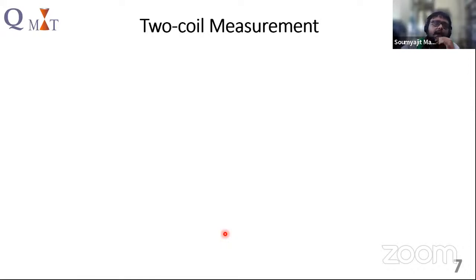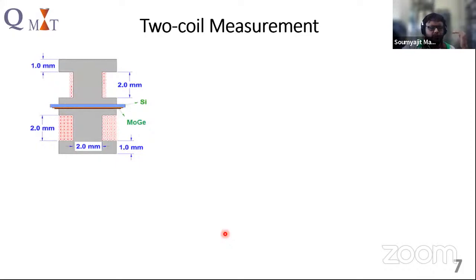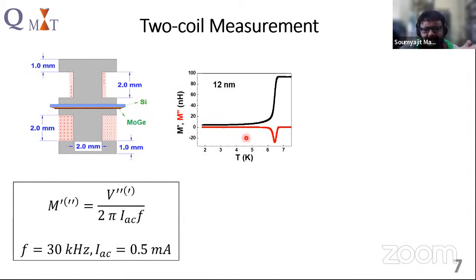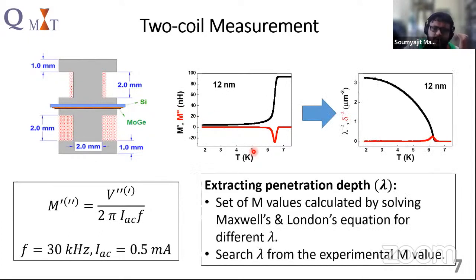And now we are going to the two-coil measurements. In this measurement, we place the sample in between two coils, and we pass a small AC current through the primary, and we pick up the voltage in the secondary. The response of the superconducting sample is captured in the mutual inductance. From that we can extract the penetration depth by solving the Maxwell equations and the London equation for the whole setup, because we have the coil parameters. So that's the measurement part.